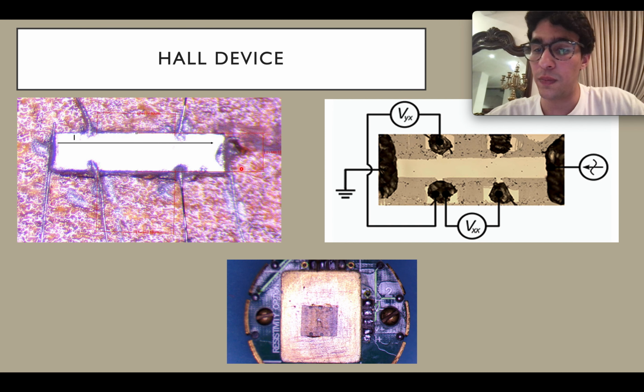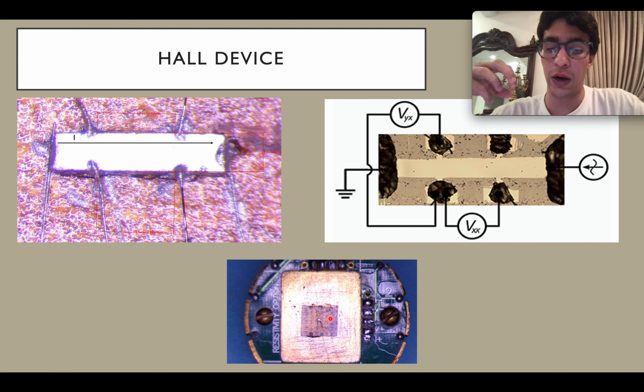So this is a sample I prepared which resembles the example figure with 6 electrical wires. These 2 wires are for current, and these 2 pairs are for Hall purposes, while these 2 pairs are for MR purposes. This sample is then placed on a puck, which can be put into our physical property measurement system, which allows us to measure the desired values.